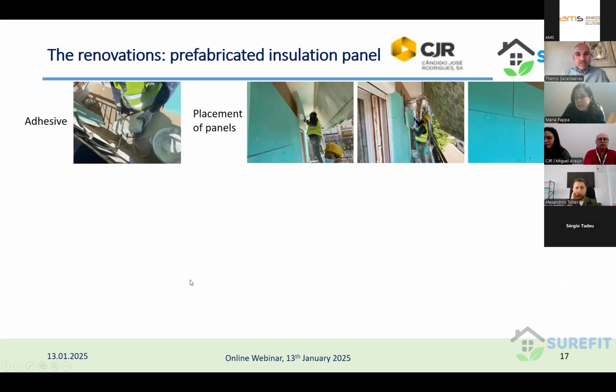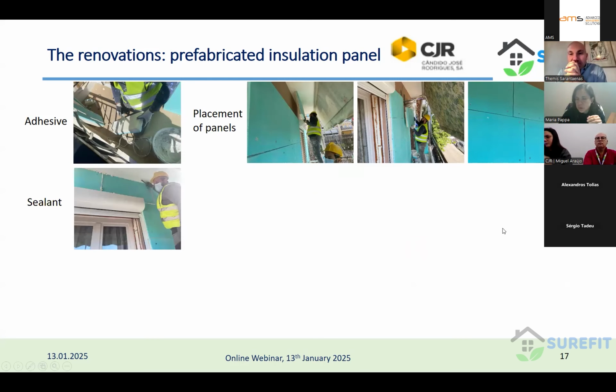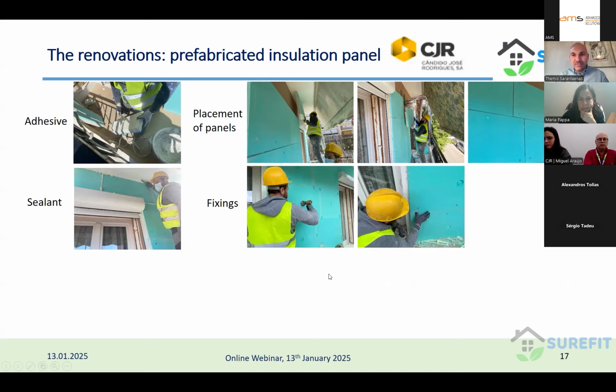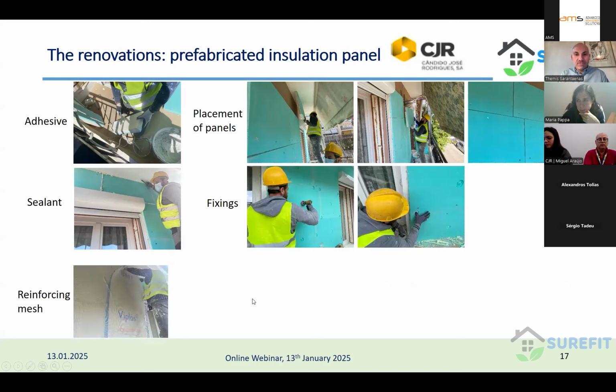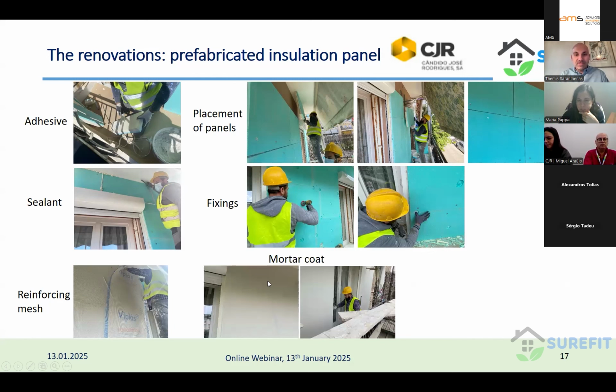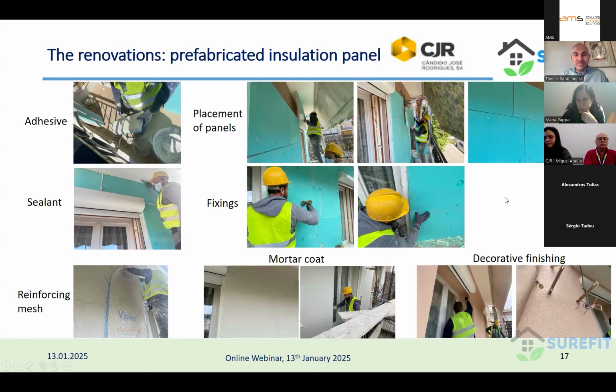So we did the installation as we do the installation of commercial thermal insulation panels, ETICS. So we put an adhesive at the beginning, we placed the panels. Of course, we had to cut them in the appropriate dimensions and also drill holes for the piping from the air conditions that were existing. We put sealant between the panels to seal the gaps. We did the fixings. We placed the reinforcing mesh, the mortar coat after that, and the decorative finishing.